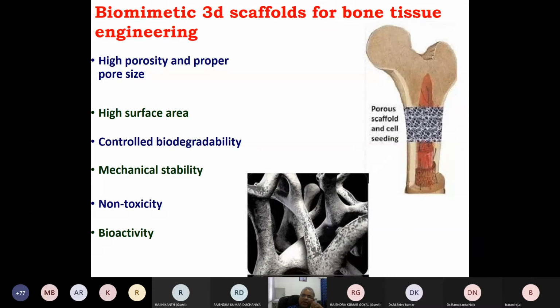So can we develop a bone-like structure with the same strength as the bone, so that we can fit it into the broken part, and the natural bone will form due to the bioactivity of this 3D scaffold that we have, that is the biomimetic 3D scaffold that we put into the bone in place of the bone. So for such a 3D bone implant or bone graft, which is biomimetic and has bone-like chemistry and properties, it should have high porosity, proper size distribution, high surface area, controlled biodegradability, mechanical stability.